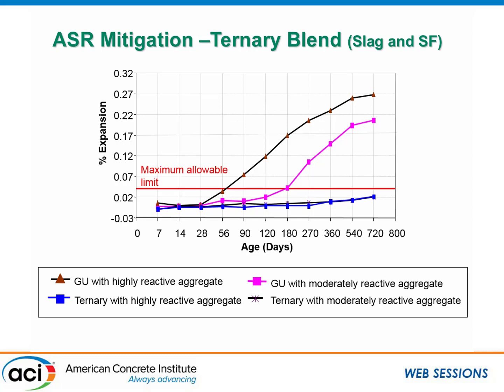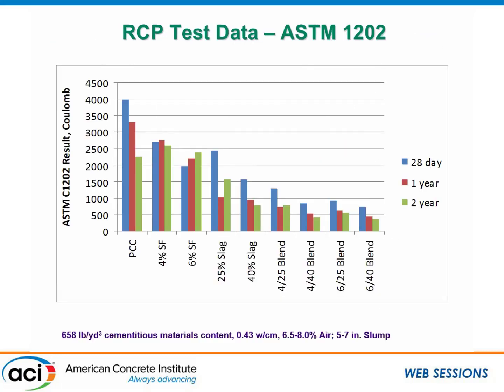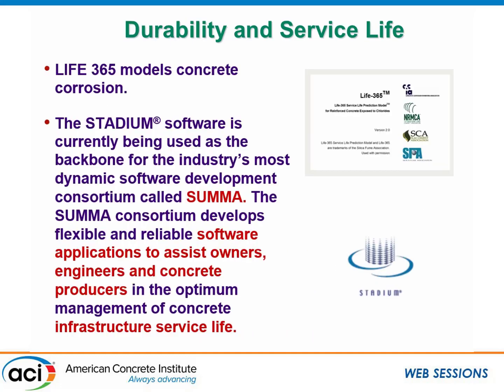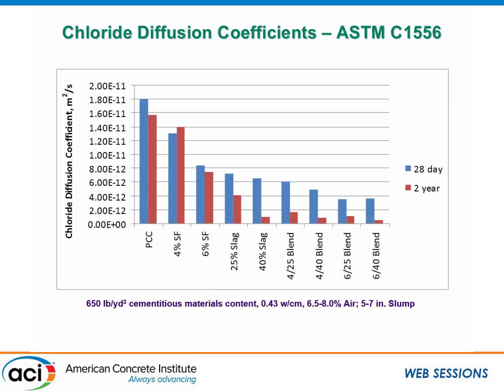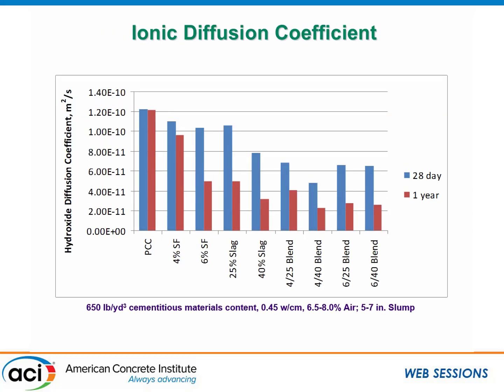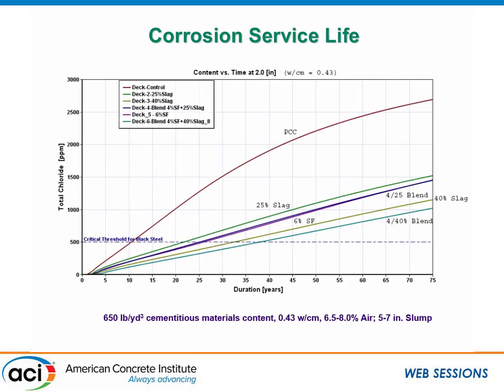Here is ASR mitigation. We can see there's 4 and 25 blends here and 4 and 40 blends, with silica fume being the 4, 25 being the slag. And we can see what would happen at the RCP data at 1 year and 2 years. So certainly we're seeing much different than we would see if we use straight ordinary Portland cement, which we see in the first column. We can also see chloride diffusion coefficients and how they're lowered over time, as we would expect. This was a 650 pounds per cubic yard cementitious content with a 0.43 water to cementitious ratio. And again, also looking at ionic diffusion coefficient,